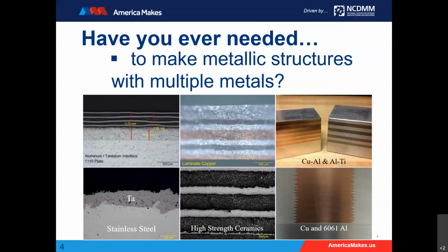The first aspect that we do a lot of work in is printing multiple materials in the same structure. Whenever you melt metal, say an aluminum, a copper, a titanium, like in the center picture there, and you melt those with an arc, with resistance, whatever, when you re-solidify that, you get a brittle intermetallic. And maybe that's what you're looking for, but 9 times out of 10, engineers are looking for something with a little ductility. With our process, since we're not melting, we're not actually mixing those two, and we avoid forming those brittle intermetallics. That means at any point during a print job, we can switch from one material to another.